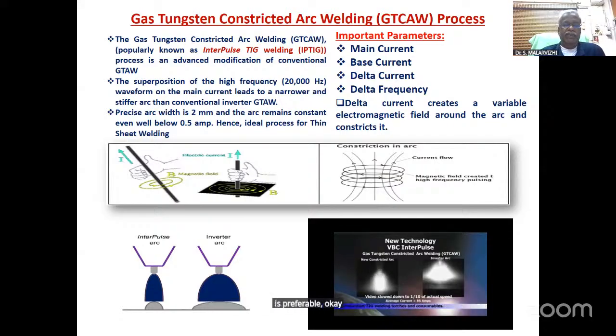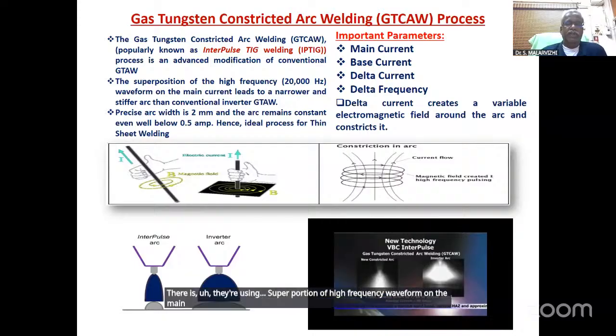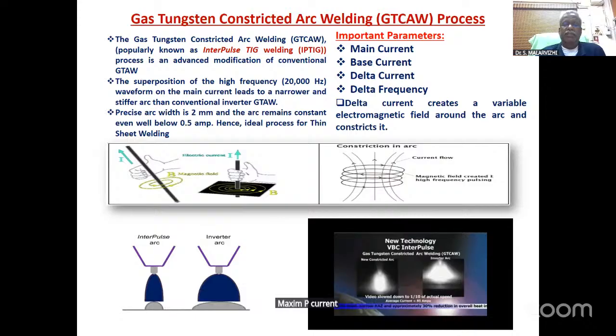Also, if you reduce the fusion zone size, the weld zone size, then subsequently the heat affected zone size also will be reduced. So in this process, the gas tungsten constricted arc welding process, also known as interpulse TIG welding process, they use superposition of a high frequency waveform on the main current. So you have the main current, the maximum peak current, and the base current, similar to pulse current welding.